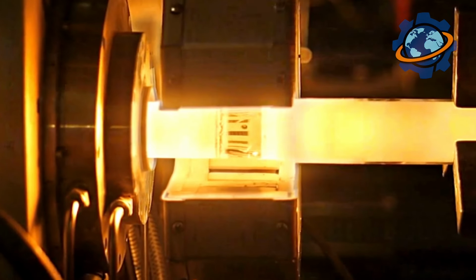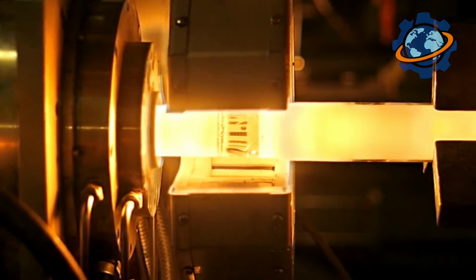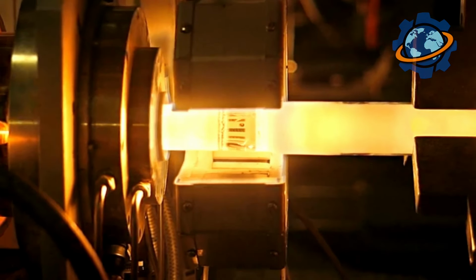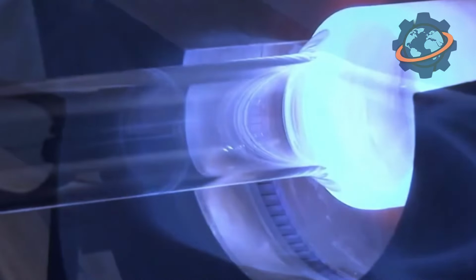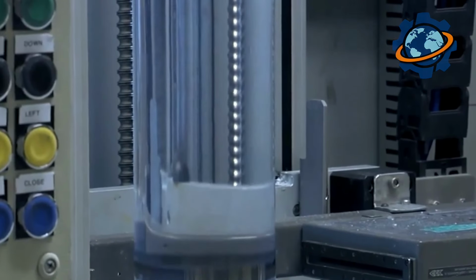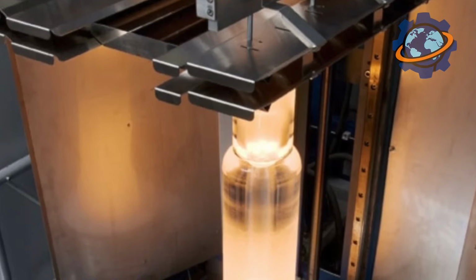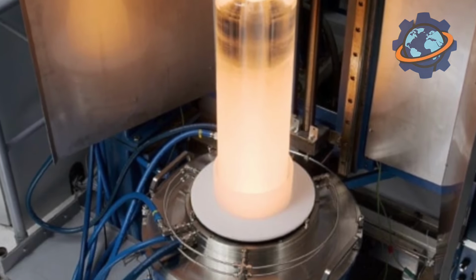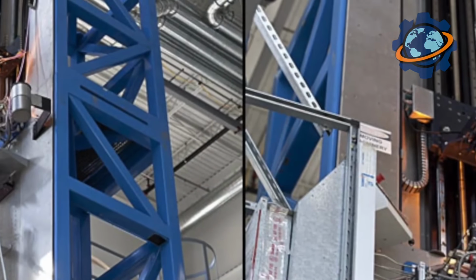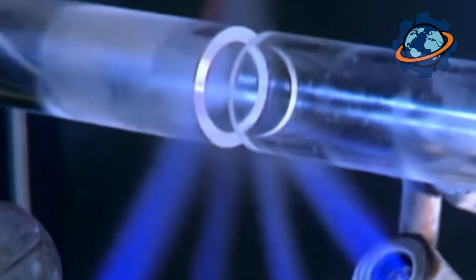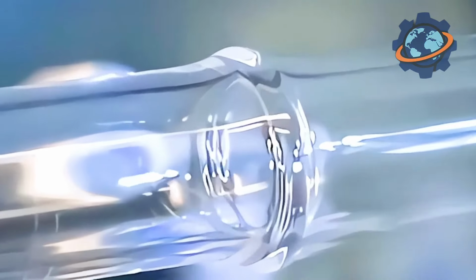When the vapors touch the hot wall of the tube, they deposit and turn into tiny droplets of glass, like dew collecting on leaves in the morning. Gradually, these droplets collect, layer by layer, until a thick layer of glass forms inside the tube. Then this tube is heated even more intensely, and it collapses into a dense solid rod, and this is our preform.